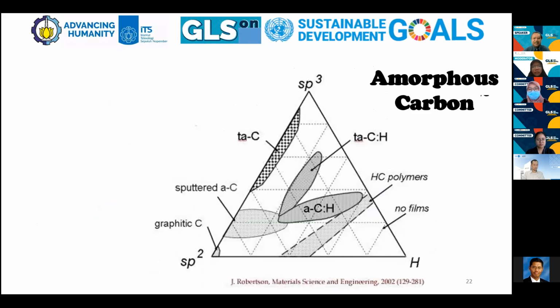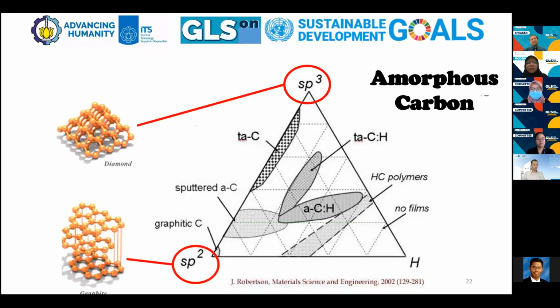Another carbon compound that does not have an ordered structure is amorphous carbon. In this ternary diagram, amorphous carbon can be composed of sp2, meaning that this orbital s, orbital p, with 2 electrons, and sp3, hybridized orbital, and also carbon hydrogen on the right side. The dominance of the sp3 bonding gives an amorphous carbon with a diamond-like structure like this. While the dominance of sp2 leads to a graphitic, graphite-like structure, amorphous carbon is generally composed of this bonding structure. This is the diamond for the sp3 hybridized structure, and this is the graphite or graphitic structure for the sp2.